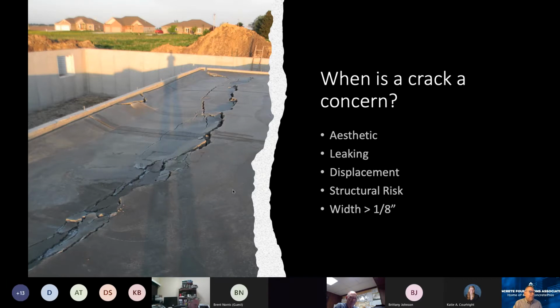It's not really all that funny, but this is certainly an extreme example of concrete cracking on the left side, because they did not backfill underneath that garage slab nearly enough, and they also got settlement and erosion underneath as some water removed through this garage slab that pulled the soil out in a step down footing condition, so they lost all of their support. Which is why so many garage slabs, even with full backfill, could be or should be designed as structural slabs to eliminate that particular concern.